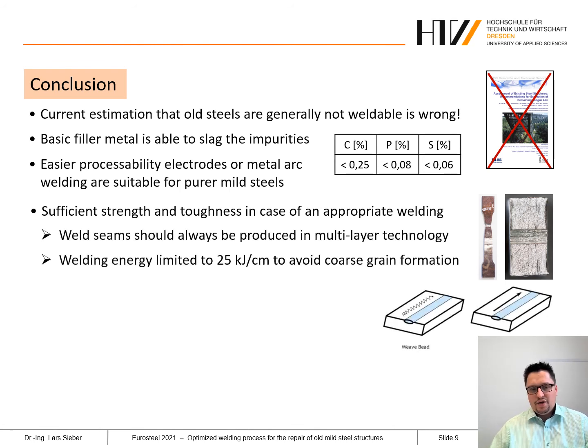That means the weld seam should always be produced in a multi-layer technique. We have to prefer the stringer beads, you can see on the right here, instead of weave beads. Weave beads you only use in case of out of position welding, for instance, a vertical welding. And the welding energy for each layer has to be limited to approximately 25 kilojoule per centimeter to avoid a coarse grain formation in the heat affected zone.